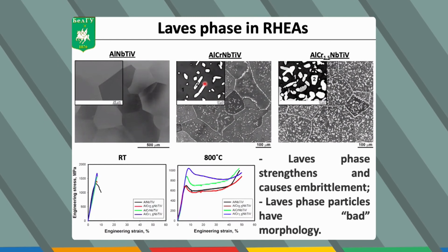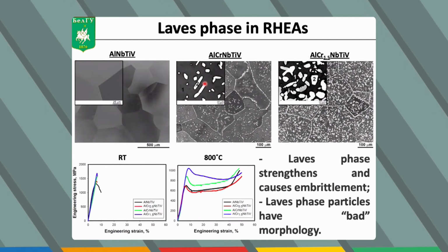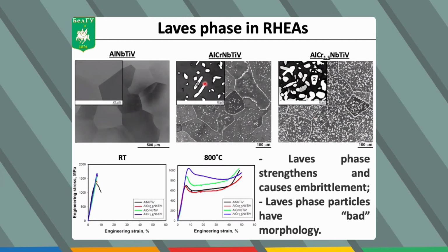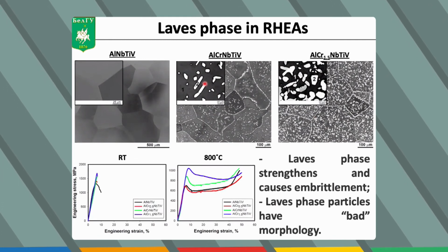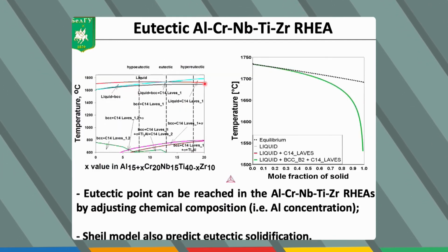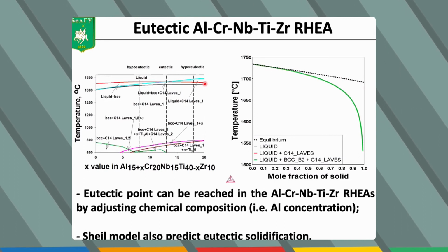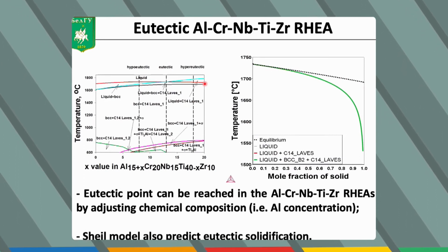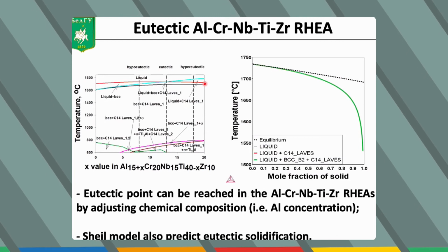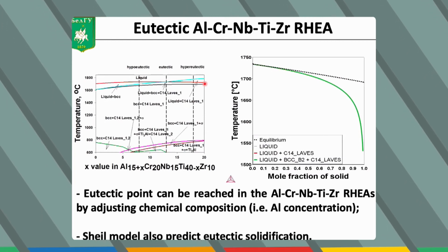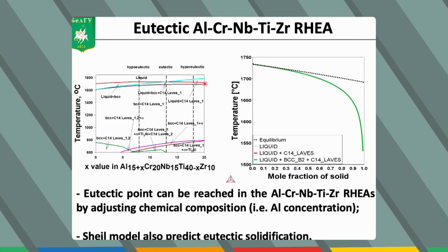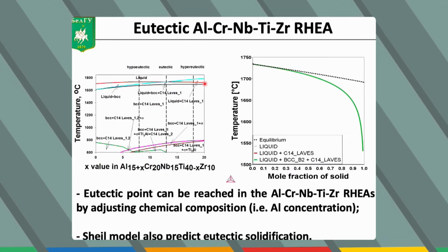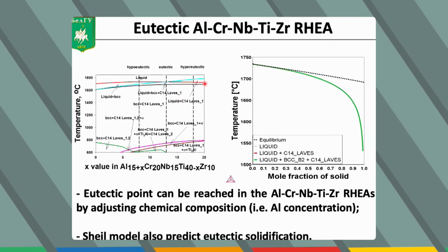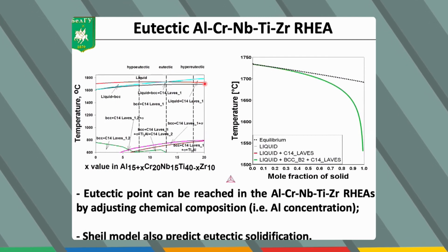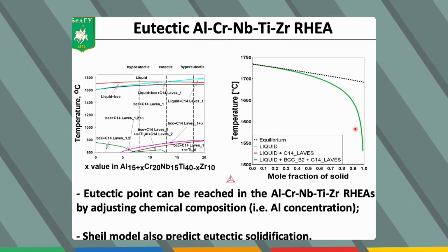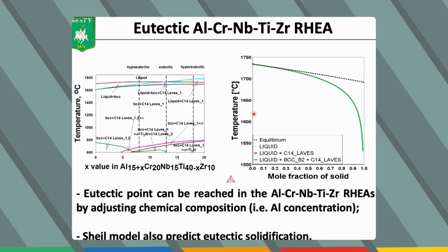So if we want to get really nice properties, we want to find homogeneously distributed particles. And what we wanted to do here is get the alloy strengthened by Laves phase particles, which will undergo the eutectic reaction. The eutectic reaction means that the alloy will solidify by the concurrent formation of two phases, here the Laves phase and the BCC or B2 phase. And actually, we performed a set of CALPHAD calculations. Here I am showing you only the final results.